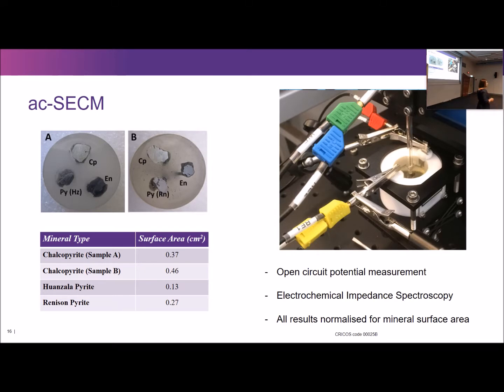And all the measurements were done in situ in the same solution that was used to then do the flotation test. So things were consistent across the board. I did open circuit potential measurements, which basically gives you the rest potential of the mineral, as well as electrochemical impedance spectroscopy, which gives you the resistivity or the resistance of the surface to electron transfer. So it's a very good proxy for electrochemical activity. And yeah, all results are normalized for surface area.